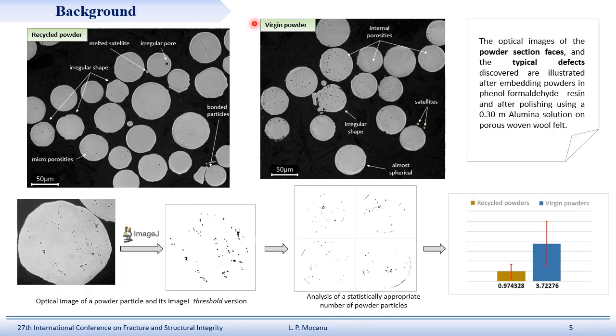Then we also investigated the internal situation and in particular the internal porosity, and we performed some image quantitative analysis in order to obtain a quantitative result, and we saw that the recycled powder is characterized by a lower amount of these tiny porosities, and this is due to the preheating inside the EBM chamber.